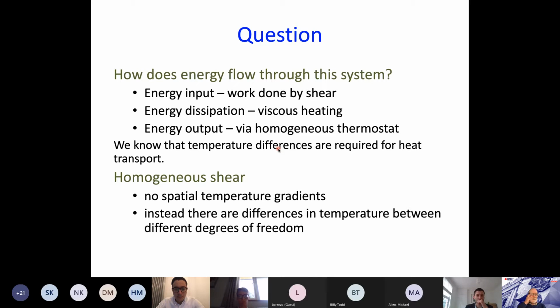But we know that temperature differences are required for heat transport. For a heat flux to occur, you really have to have a temperature difference. And in homogeneous shear, we've got no spatial temperature gradients. So instead, what we do know is that there are differences in temperature between different degrees of freedom. And that's where the temperature differences are. And I believe that that's where the entropy production occurs as well.